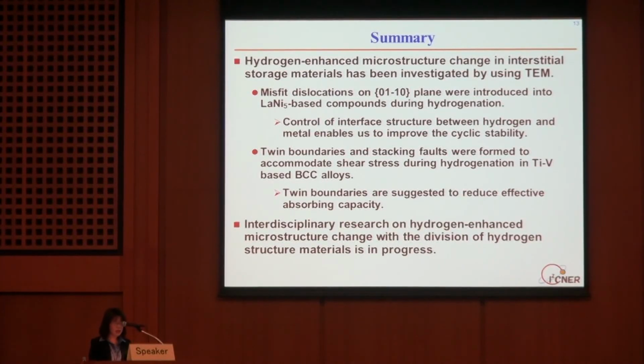To summarize my talk, the dislocation structure in lanthanum nickel 5 indicates the interface structure between hydrides and the metal lattice. This indicates that controlling the interface structure enables us to improve the cyclic stability of lanthanum nickel 5-based alloys.